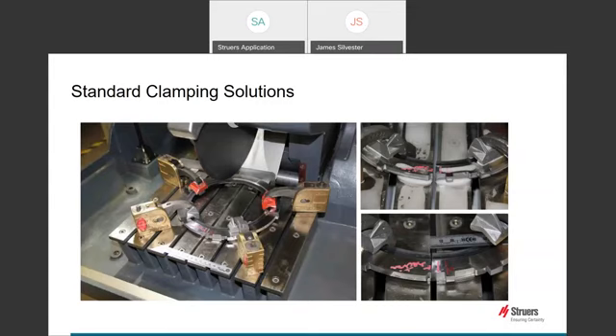Whilst there are several ways of clamping the part during cutting, using the readily available vertical clamps would be the most flexible for different size parts and allows easier maintenance and replacement should changes need to be made. Our particular solution involved using 4 standard vertical clamping tools in this case. Swivel shoes with angled feet were able to grab onto the inside edge of the ring to avoid this pinching effect. Using the standard flat swivel shoe did not stop this pinching effect, as the friction force alone was not sufficient to prevent movement of the part.